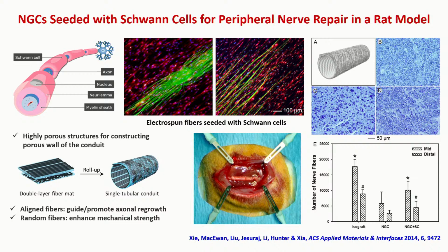So in this case, if you count the number of nerve fibers in that cross section, you can see for this group, this is going to be the middle point, and this is going to be distal. Distal is this, middle is over here. So you can see at least for the middle point, the number of nerve fibers is almost half of the autograft or isograft. It's not perfect, but it's a significant improvement compared to just the conduit itself without Schwann cells. So you do see the positive impact coming from the Schwann cells.